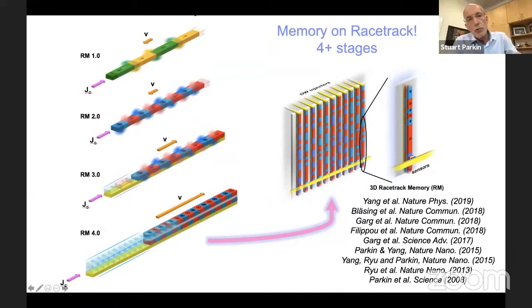Originally, the concept was to use soft magnetic materials. This is, if you like, racetrack memory 1.0. In those cases, you pass current into the wires, and the domain walls move in the direction of the flow of spin angular momentum created by polarizing the charge current through spin-dependent scattering within the magnetic layer itself. When you completely transfer all the spin angular momentum from the current to the domain walls, the maximum potential velocity is about 100 meters per second for current densities that don't significantly heat the racetrack. That's what we demonstrated in Racetrack Memory 1.0. We could achieve nearly complete transfer of the spin angular momentum from the current into the magnetic system. That was quite a surprise. It's achieving velocities of about 100 meters per second.